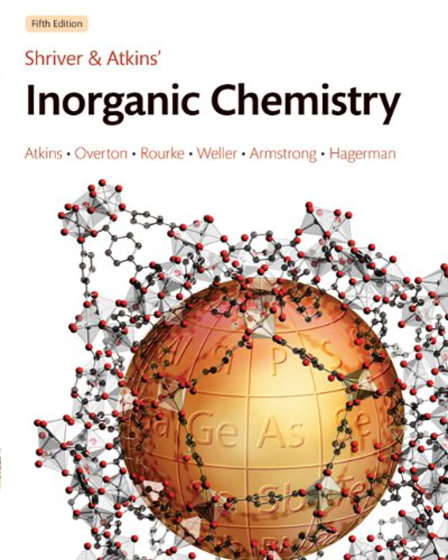It's a major theme. This size difference also shows up in thermal stability. Lithium carbonate decomposes to the oxide and CO2 at a relatively low 650 degrees C. Whereas the others are more stable. Much more. Sodium carbonate melts above 800 degrees C before decomposing, and rubidium carbonate is stable up to nearly 1,000 degrees C. Again, the larger cations provide greater stability to the large carbonate anion.